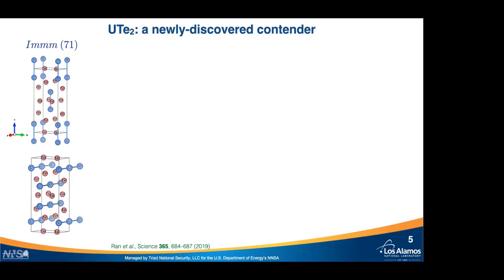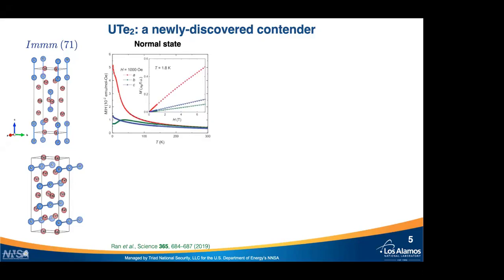So this material was known for quite a while, for decades, but it was only discovered to be a superconductor last year. So here's the reference, Nick Butch's group at the University of Maryland and NIST. They cooled down this material below 2 Kelvin, and they found out that it is a superconductor. So let me tell you first, in the normal state though, here's the magnetic susceptibility versus temperature.